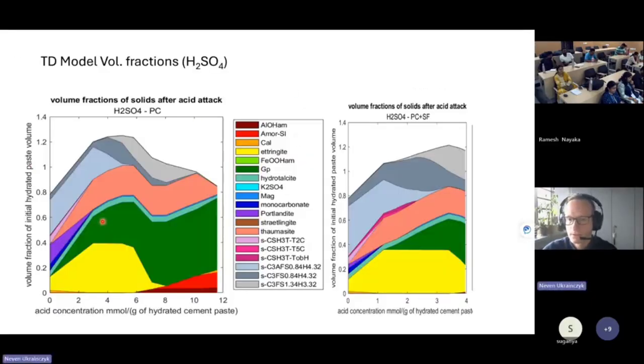So these are the volume fractions. You can see with sulfuric acid how the phase assemblage changes. This you can also now model easily in the GEMS app online. I will show you this. Basically, you are dissolving Portlandite and CSH phases, but you are precipitating gypsum here. More and more gypsum. And with silica fume, you basically have just less Portlandite at the beginning. The Portlandite is lilac here. So we don't have so much Portlandite. So that's the difference.